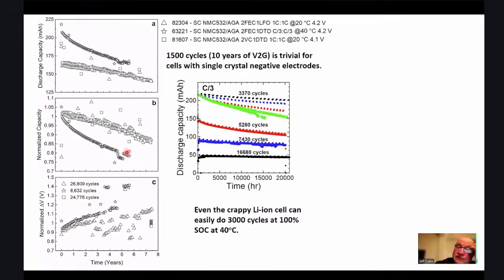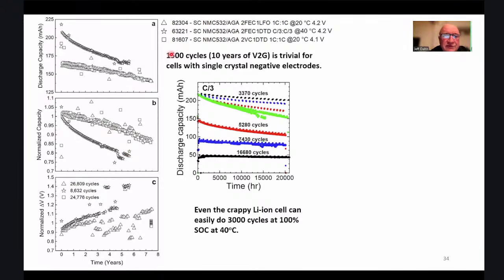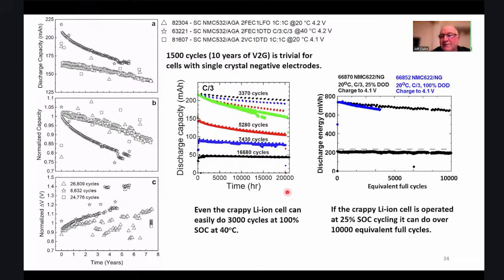You know, so vehicle to grid is no problem. 1,500 cycles, 10 years of vehicle to grid is trivial for cells with single crystal positive electrodes. That should say positive, not negative. And even the crappy lithium-ion cell that I showed you at the beginning can do 3,000 cycles at 100% state of charge at 40 degrees C. And you only need 1,500 for 10 years of vehicle to grid and driving, right? So this is easy, even if the cell was at 40 degrees the whole time. And if you operate at 25% state of charge cycling, you can do over 10,000 equivalent full cycles. So I think vehicle to grid is compatible with most batteries that are in vehicles today.